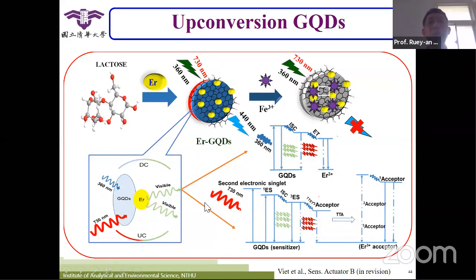You can also use it for upconversion. Upconversion is quite new at this moment. We always know that graphene quantum dots can do down-conversion. For the optical property, we use a low wavelength of 360 nm and they can emit at 440 or 460 nanometers. That is what people would like to use. But one characteristic of GQD is that they have the upconversion property. When you use long wavelengths like 730 nm, they can still emit at around 440 nanometers. What's the advantage of that?